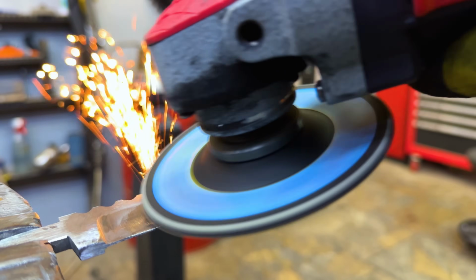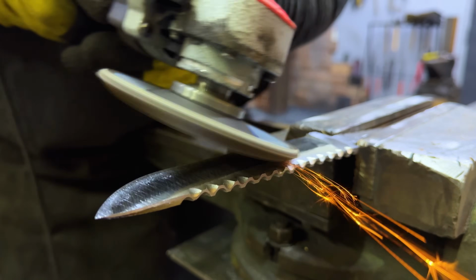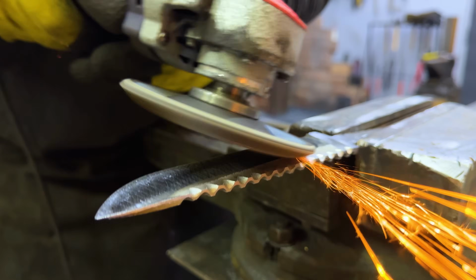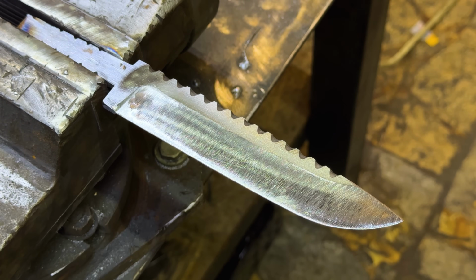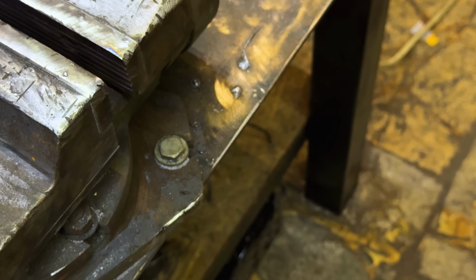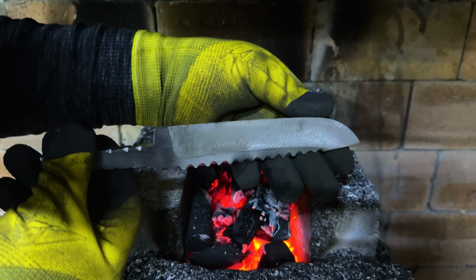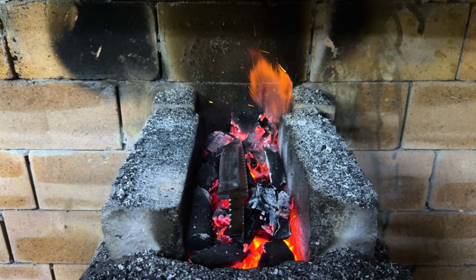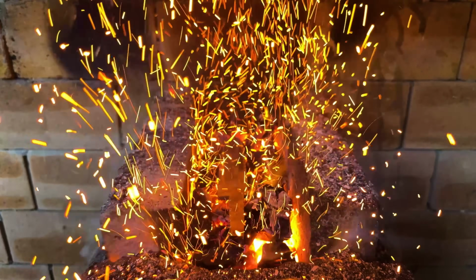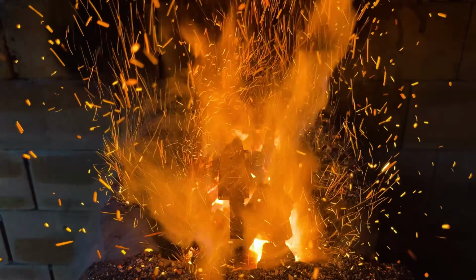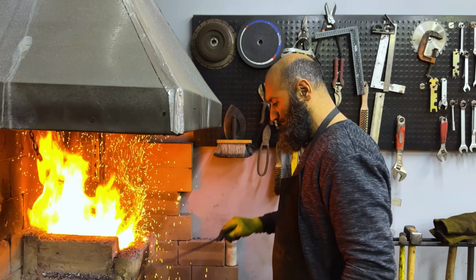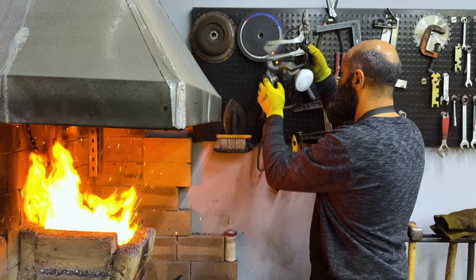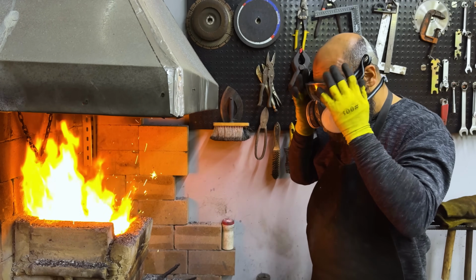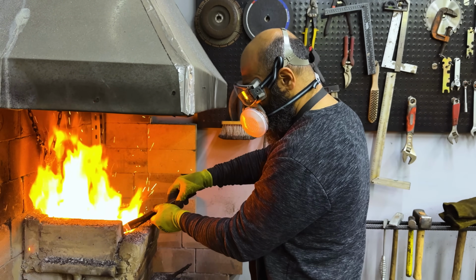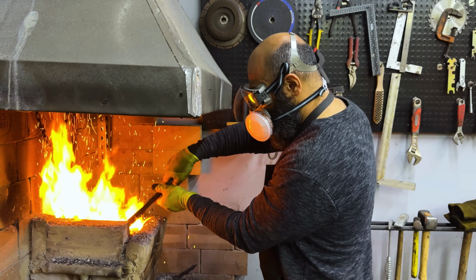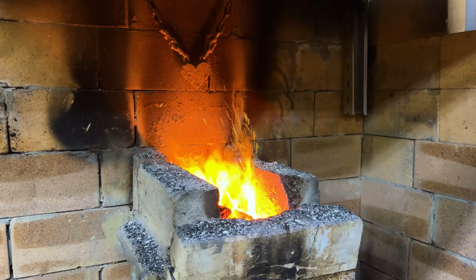This is the hardening heat, critical, where we need to hit the non-magnetic point and maintain that heat for a few moments. We need to allow the carbon in the steel to fully dissolve into the solution, forming austenite, usually about 815 to 870 degrees for most high-carbon steel. If it's too hot, the grain structure grows too large, making it brittle, too cold, and it won't harden fully. Precision is everything. Note the respirator. The oil quench is coming, and you don't want to breathe those fumes.